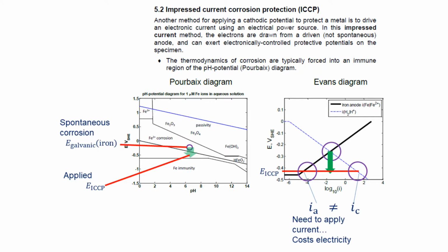The cost of that is that the hydrogen reaction, the hydrogen evolution on the iron surface, is now proceeding at quite a fast rate, and the currents no longer balance. The anode current density is no longer of the same size as the cathode current density, because there's much more of the cathodic hydrogen evolution happening.